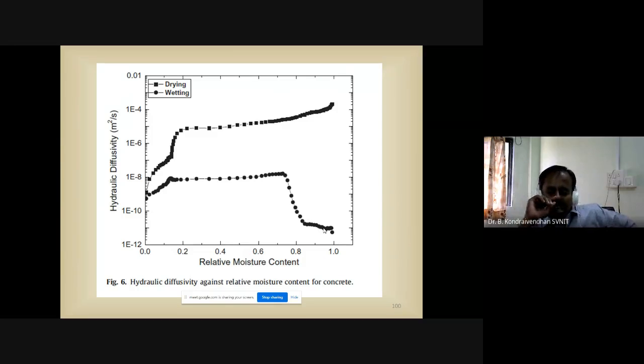Then he also extended it to permeability and hydraulic diffusivity. He plotted the hydraulic diffusivity versus relative moisture content for both wetting and drying cases. So this guy has done only experimental work, but by using the experimental pore size distribution parameters, he calculated the compressive strength, permeability and hydraulic diffusivity. He has not done any modeling. Actually there is a scope, so one can do modeling for the concrete pore size distribution parameters also. Maybe in future I am planning to extend this work for concrete also.